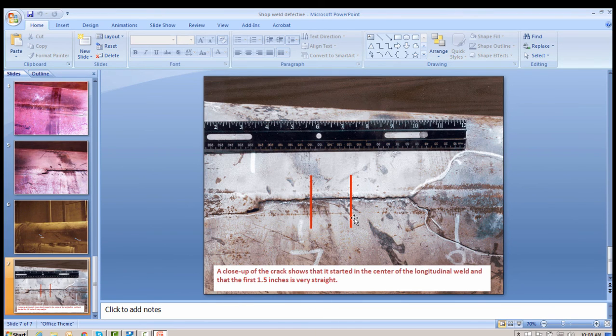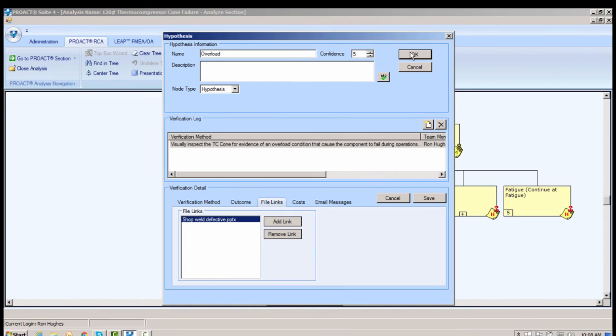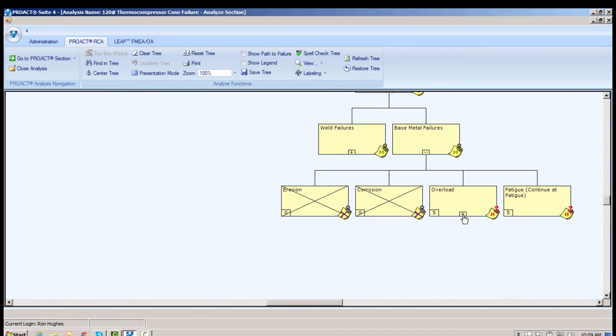And when we get over here, this is the initiation point. The way we know this is the initiation point is we look at the chevron marks when we cut this thing up, and you're going to see where we cut it up. The chevron marks go in this direction, and they go in this direction. Where the chevron marks come together, the arrows come together, that's the initiation point. The initiation point is right in the center of this very straight crack here. So that's where the failure started, and it propagated that way, and it propagated that way. So it's definitely overloaded.